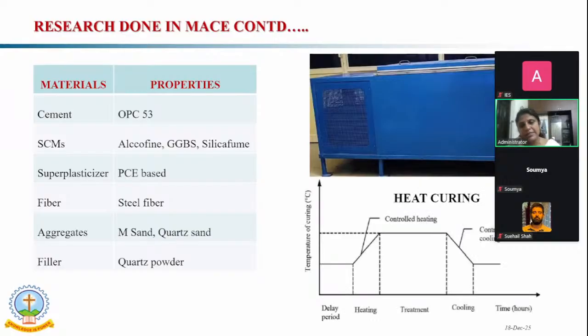Then what type of curing we have followed: in the case of the parametric study, we have considered many curing temperatures, like 90 degrees centigrade as well as 60 degrees centigrade. And also we have varied the delay period. That means after casting, after 24 hours, we demolded the specimen. Delay period means when it has to be put into the steam curing after that. We considered 24 hours, 48 and 72 hours delay periods. With all this, we got that the 48 hours delay period shows the better performance.